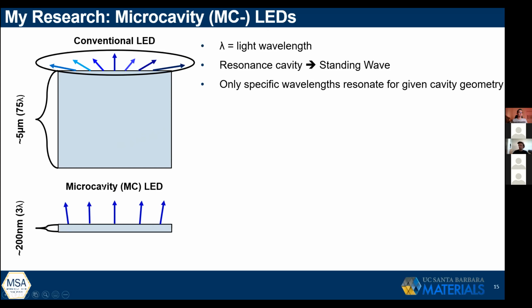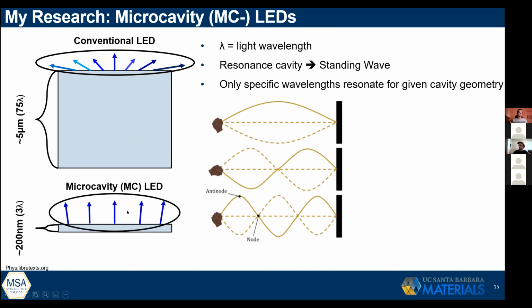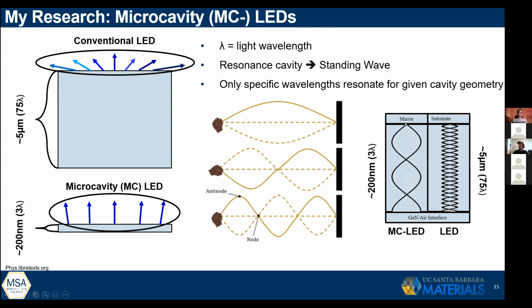The microcavity is basically a standing wave where you have two fixed ends. And because of this, you're able to extract your light better, because at this GaN-air interface, where GaN is your LED, when you're at a maximum, when you're at an antinode, you're able to extract light more effectively than if you're anywhere else. That's easier to do with a microcavity because you're designing specifically for this purpose. Whereas with a conventional LED, it's so much thicker, there's so much variation that it's much less likely to happen.